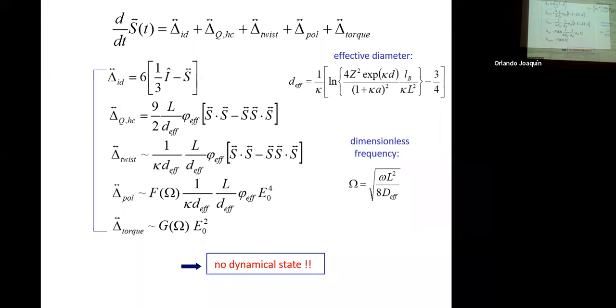And then you have a twist effect, and that is the effect if you have two rods like this, and you put them together, and when they have the same alignment, of course the interaction energy is very, very high, because you have an enormous overlap of double layers.